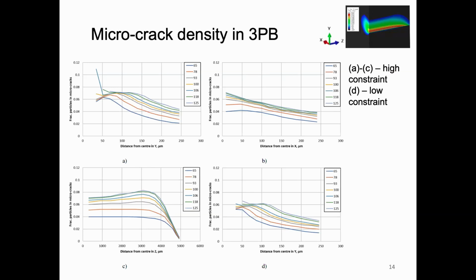So now what we did is we took this model and we used it for all positions. First of all, this was one realization. We did 100 realizations, and the results here are the average of that. So these are the averages of 100 realizations, 100 distributions of particles. This is the distribution of microcrack density ahead of the crack, perpendicular to the crack plane, and along the crack line, in a high constraint geometry, and this is ahead of the crack in a low constraint geometry.